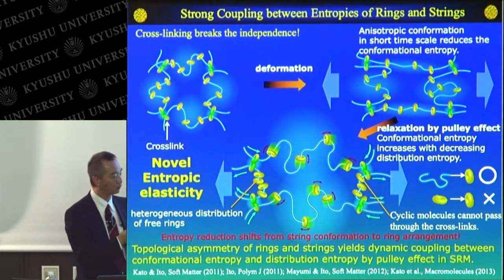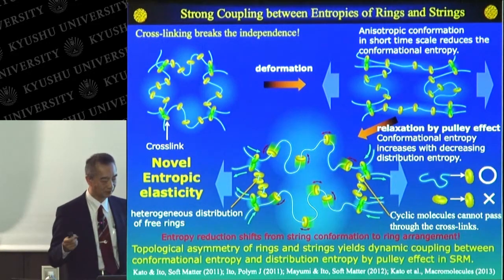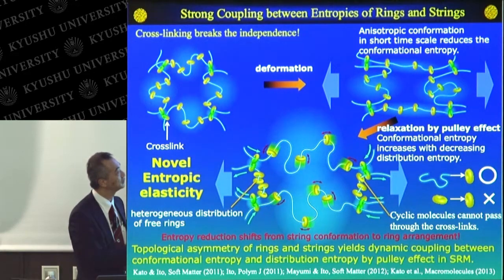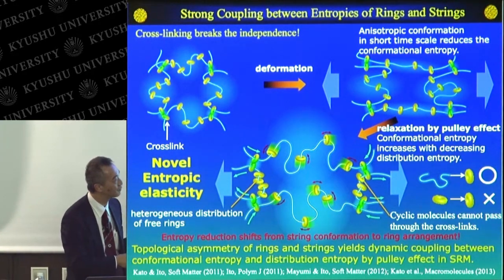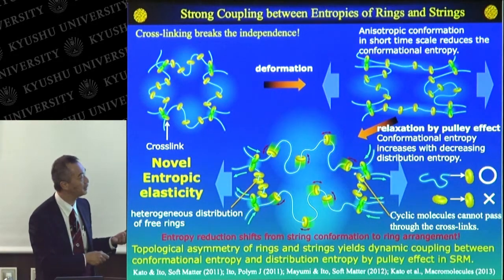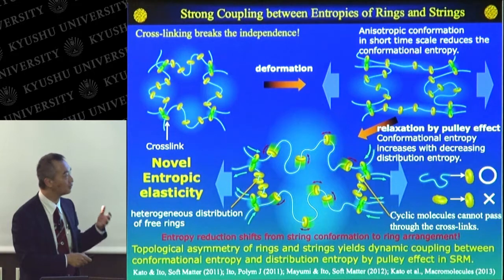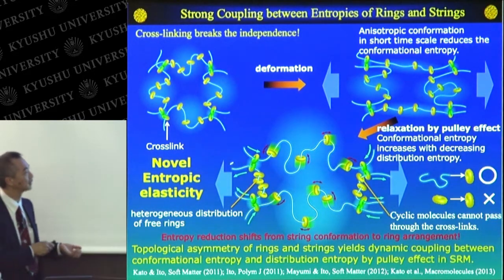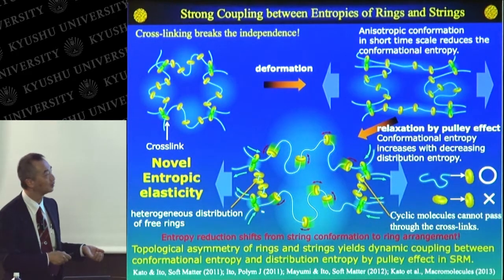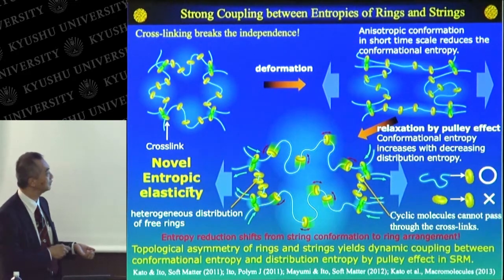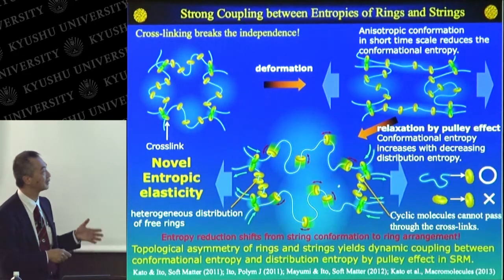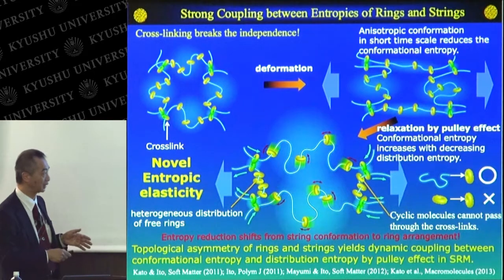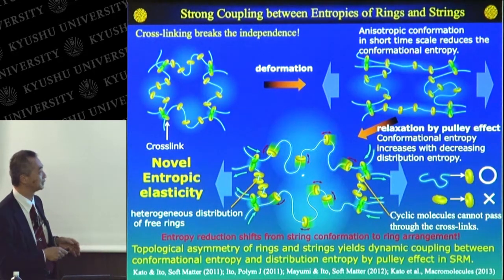On the other hand, when the sliding material is stretched in this direction, the polymer chain is deformed in short time scales, and then the pulley effect starts to occur. But what is important here is that the polymer chain can pass through the crossing point, but these free rings cannot pass through the crossing point. So the pulley effect yields some heterogeneous distribution of free rings after stretching. In this case, the entropy of rings is reduced drastically, which yields a novel entropic elasticity.